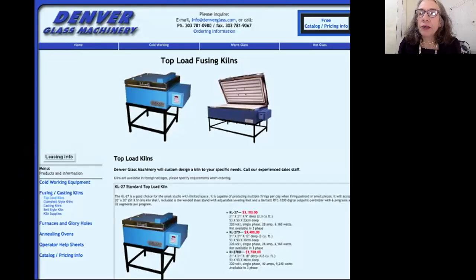Vitreous paints and Fusemaster enamels fire on at about 1250 degrees Fahrenheit, which is 676 Celsius, a mere fraction above 666, I'm sorry to report. Silver stain fires lower, at about 1050 degrees Fahrenheit or about 565 Celsius. If you are interested in getting your own kiln, I personally use a top-loading fusing kiln just like this one from Denver Glass Machinery. I have had it for decades with absolutely no need to do anything. It is a real warhorse of a piece of machinery.